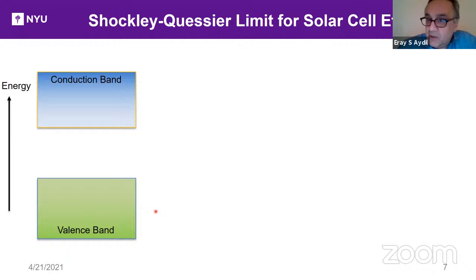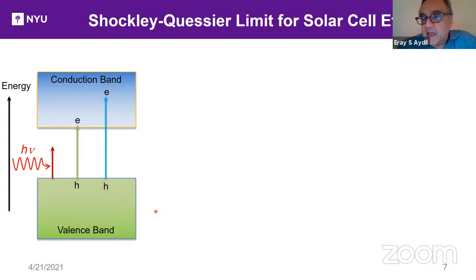But as you may know, solar cells work based on the principle of exciting electron-hole pairs across a conduction and valence band gap. And if you have a spectrum of energies of photons, there are some possibilities. One is that the photon has energy less than the band gap, in which case you don't use those photons. So some of the sun's energy we throw away. If it has the band gap energy, then it can create an electron-hole pair, which can then be accelerated and extracted as current. If the energy is greater than the band gap, then we excite hot electrons and holes, and those cool very rapidly by colliding with the lattice atoms and exciting phonons, which is basically heat, and that is energy lost as heat.